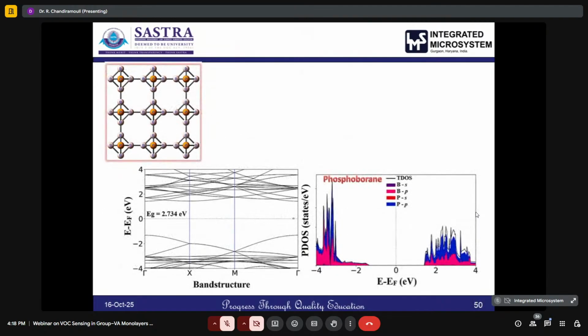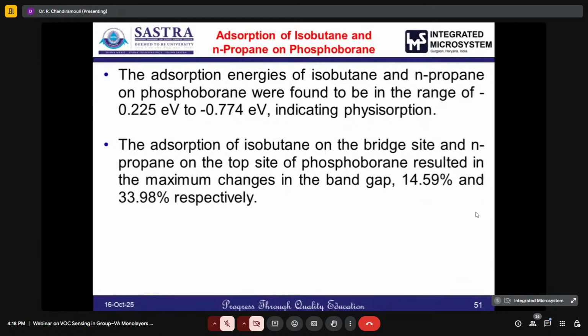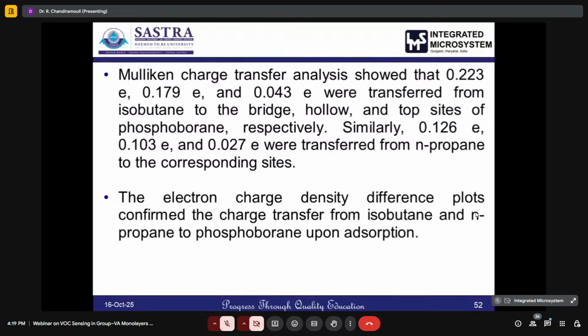The structure and band structure of the pristine phosphoborane are shown here, along with the adsorption of isobutane and n-propane on phosphoborane. The adsorption energy of the LPG gases isobutane and n-propane is found to be in the range of -0.225 electron volt to -0.774 electron volt, indicating physisorption. The adsorption of isobutane on the bridge site is found to be optimum, and for n-propane the top site is found to be optimum. The Mulliken charge transfer analysis also showed that 0.223, 0.179, and 0.043 e are transferred from isobutane to various sites. Similarly, 0.126 e, 0.103 e, and 0.027 e are transferred from n-propane to the corresponding sites.